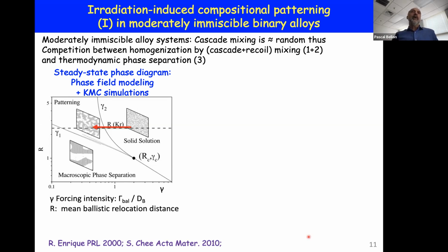When we model the evolution of an AB alloy or model alloy using phase field modeling or kinetic Monte Carlo simulations, I'll show you some illustrations later. What we found is that we can build a phase diagram of the steady states that the alloy would reach under radiation. Here we kept temperature and composition constant. But in addition to those 2 axes, which would be the only ones we would see in an equilibrium phase diagram, in this steady state phase diagram we also have this forcing intensity, which is the rate of ballistic jump frequency over thermal jump frequency. And along the vertical axis, we have the mean ballistic relocation distance, normalized by the nearest neighbor distance, so it's R over lambda from my previous slide.